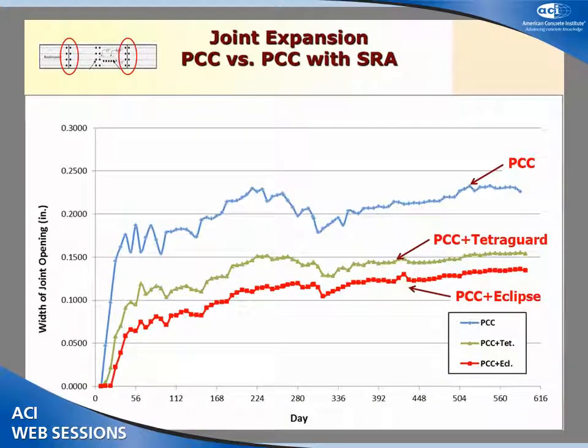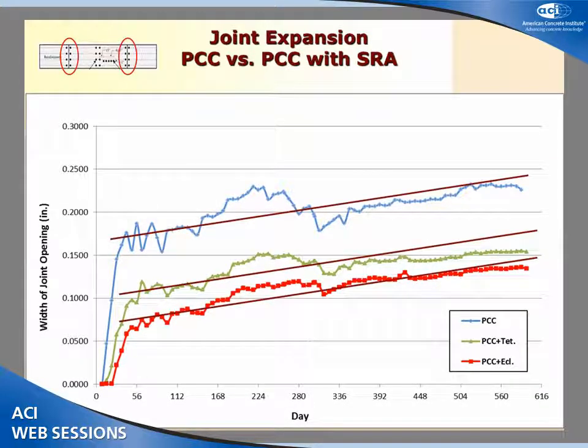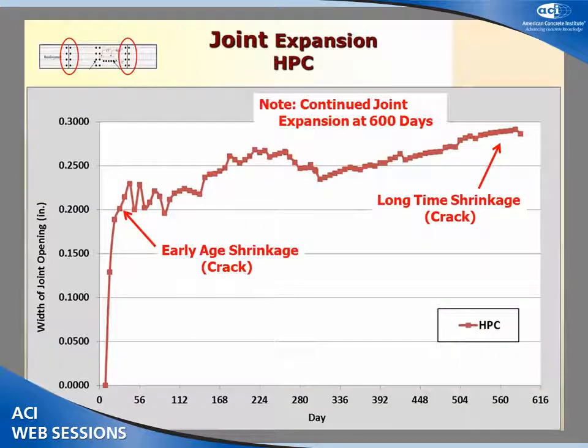In this graph, I wanted to show you Portland cement concrete versus the shrinkage reducing admixture we used. If we just compare this, you can see that these graphs are parallel with an offset by the initial shrinkage, or we can say that these graphs are, with the exception of the first few weeks, positively correlated, and that they have the same trend.